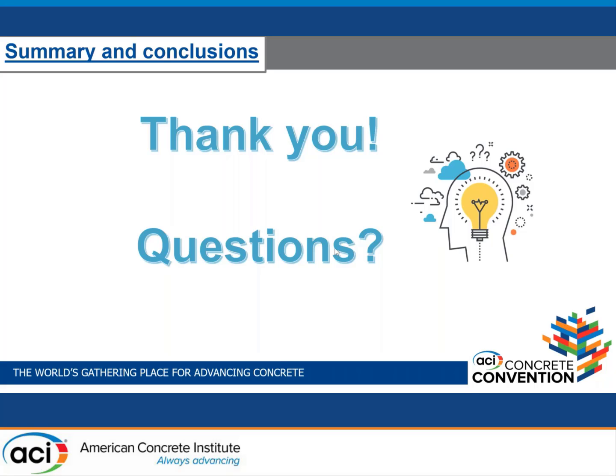Okay, great. We have a comment also: for UHPC to be more widely used, commercial labs need to learn these tests. What would you recommend as far as the adoption of these test methods is concerned? So for UHPC to be widely used, it's true that some test methods have to be standardized. And one of the main reasons we're studying the DEWS test method is that for the direct tension test method, you need a machine that's able to perform tension tests, and these machines are usually more expensive. With the DEWS test method, if we can prove that this is a very reliable test, the labs will only need a compression machine to obtain the tensile strength of the UHPC, which would be cheaper and I believe more accessible for labs.